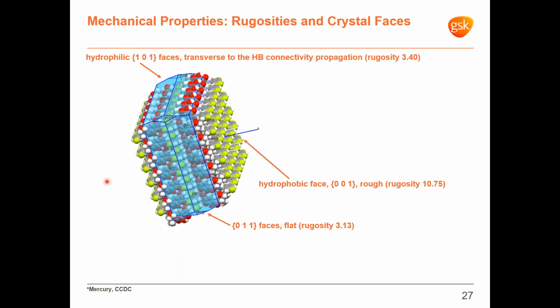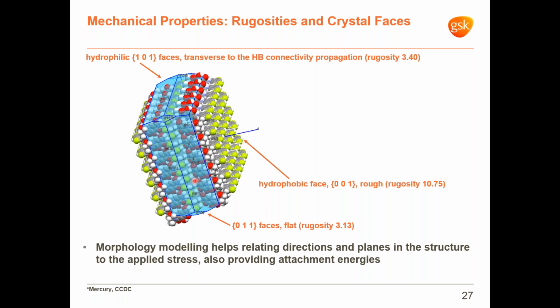In the absence of clear slip planes in the structure, rugosity is a useful descriptor accounting for steric hindrance towards slippage along the different planes. This cartoon describes calculated rugosities for the most significant directions in relation to the main crystal faces based on the BFDH crystal morphology model. And beyond this, morphology modeling helps linking the different planes and directions in the structure to the geometry of the crystalline particles, allowing to predict their relative orientation towards the applied mechanical stress in our processes.